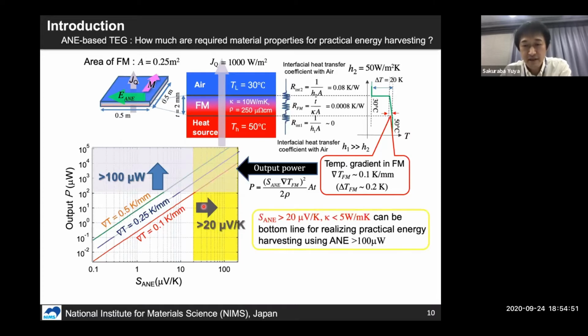Of course, this is one example of calculation based on this specific model. But what we can find from this kind of simulation is that we need to realize at least a few tens of microvolt per Kelvin from the anomalous Nernst effect for realizing the energy harvesting technique.